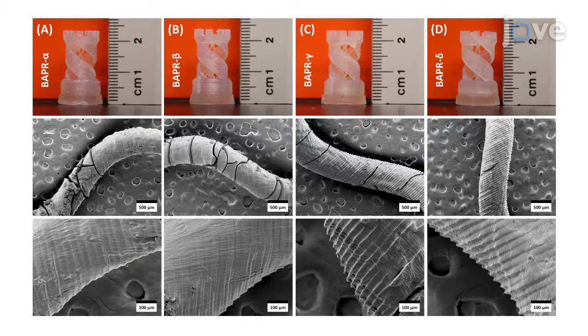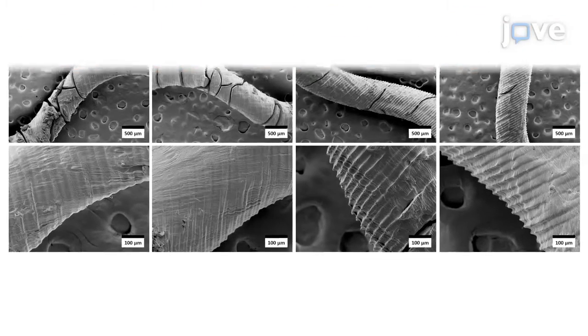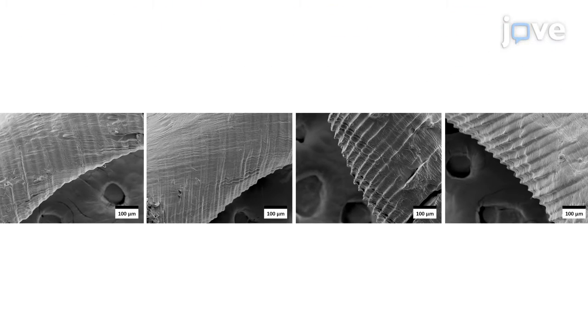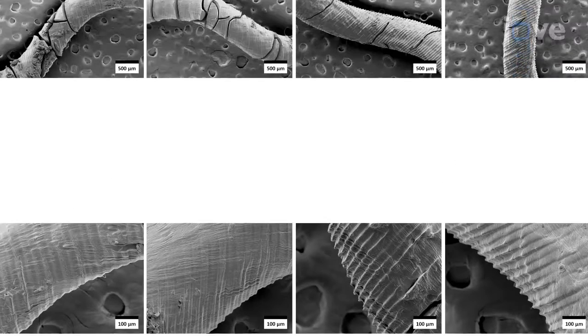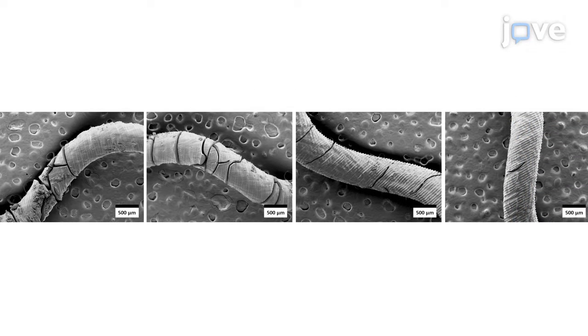The smooth surface and high feature resolution of the complex-shaped prototypes is revealed by the electron microscope. The serrated vertical edges of the helices arise from the layer-by-layer SLA printing process, in which the top of an exposed layer receives a larger UV dose compared to the back of a layer. The extent of surface cracking is related to the initial resin viscosity.